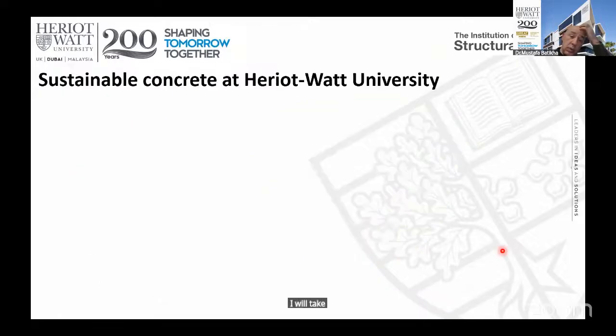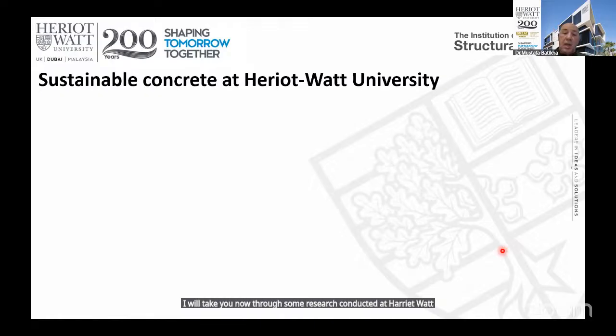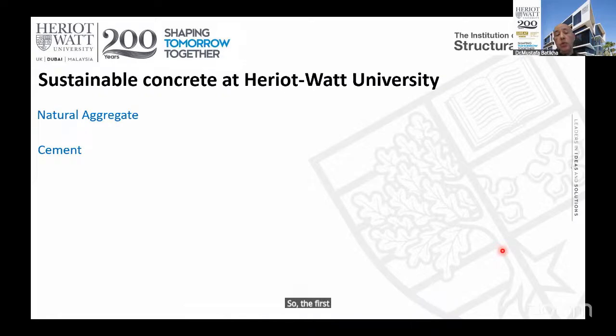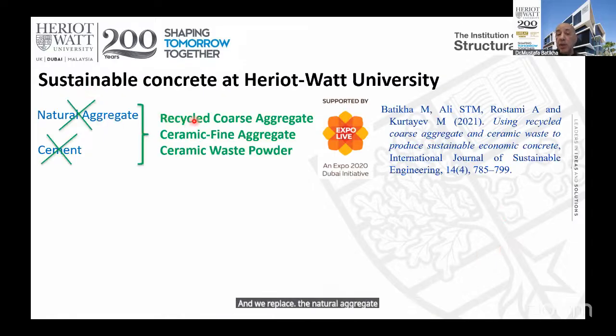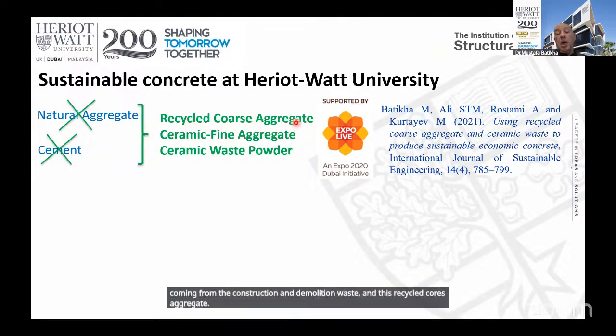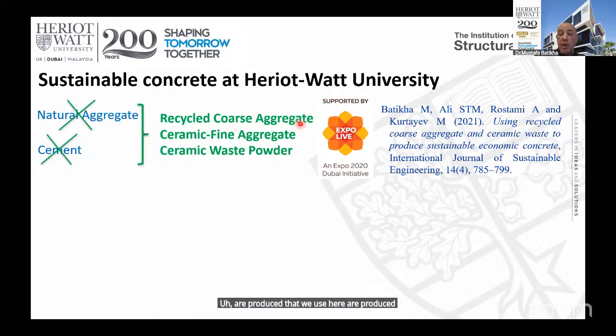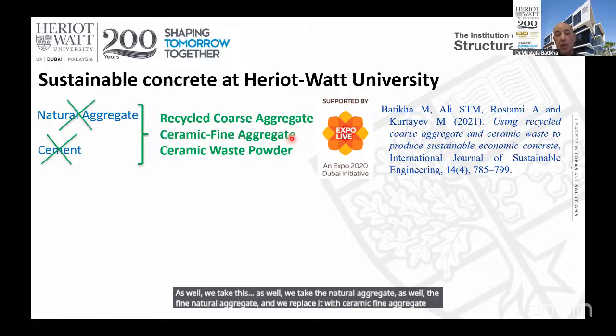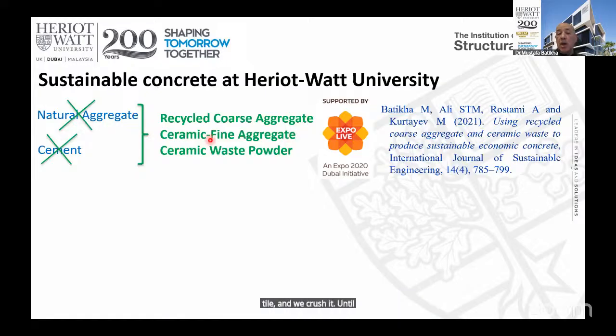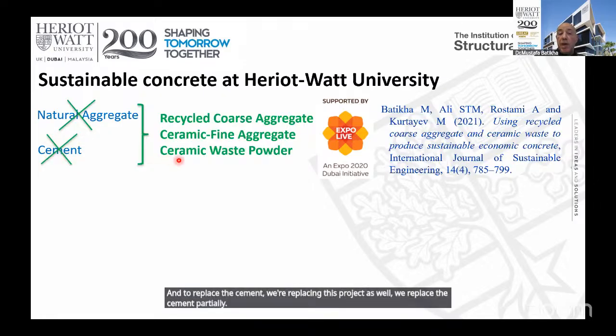I will take you now through some research conducted at Heriot-Watt University. In the first research, we have natural aggregate and cement, and we replace the natural coarse aggregate by 100% recycled coarse material coming from construction and demolition waste. The recycled coarse aggregate we use here is produced in Bee'ah company in Sharjah. We also replace the fine natural aggregate with ceramic fine aggregate. We take the ceramic tile and crush it until we obtain the fine aggregate. And to replace the cement, we replace it partially by ceramic waste powder.